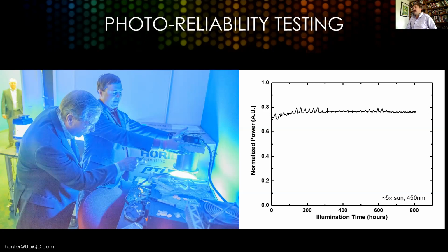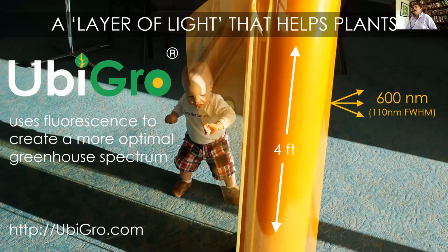And at about 5 times the intensity of blue light that's in the sun, at 450 nanometers, you can see that there's essentially no change in the performance of the device over these hundreds of hours. And we've actually gone out to 3,000 hours in some tests, but I wanted to show one of our most recent scans here. And I believe this data will be in the supporting information of the paper that's about to come out. So that wraps up the story I wanted to tell about our windows.